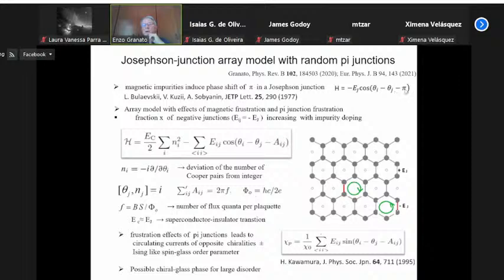A phase shift of pi here is equivalent to having the Josephson coupling negative. So we can model the effect of the junction by considering an array with the effect of magnetic frustration, which is also called pi junction frustration, by a fraction x of negative junctions, which increases with the impurity doping. So the increased impurity doping increases the number of negative junctions, which leads to some important effects I will just describe. Now, the model is the same, except that now A_ij is equal to 0 or pi.